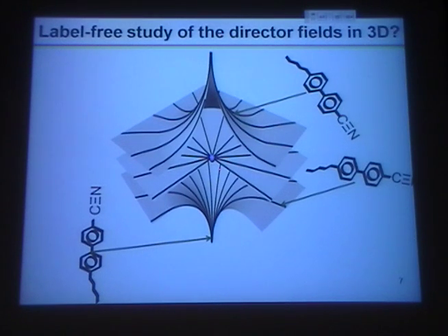And so if liquid crystal molecules follow those director field lines, we could tell what those director field lines are, provided that we would know how the CN chemical groups, triple bonds, are oriented, for example, right? Because they are along the director field on average. Also, the transition dipole moments of fluorescence corresponding to those benzene rings in the 5CB molecules, right?